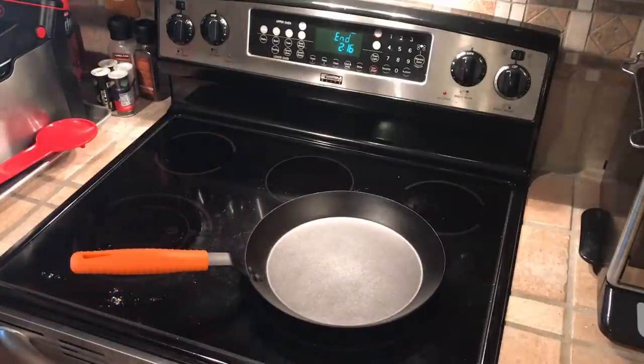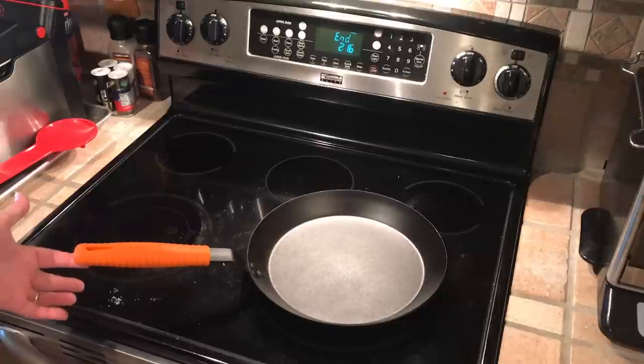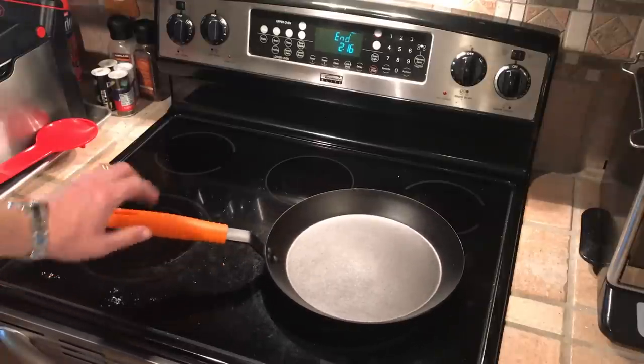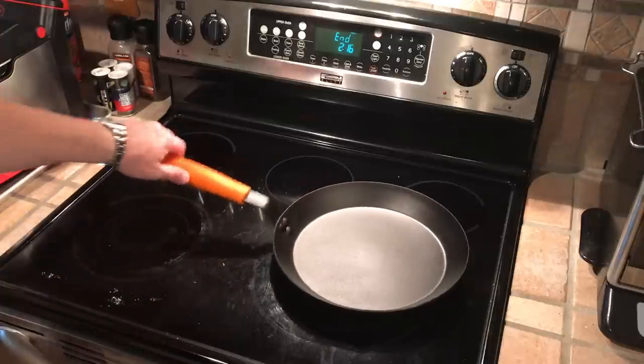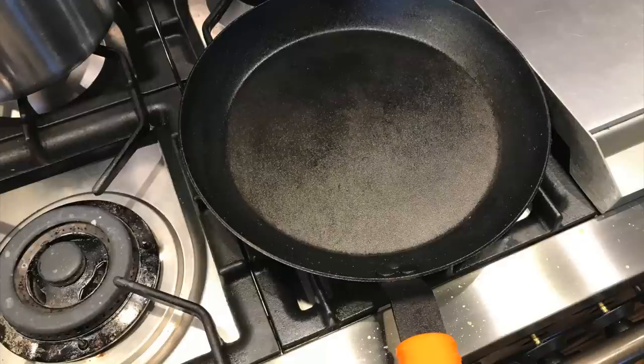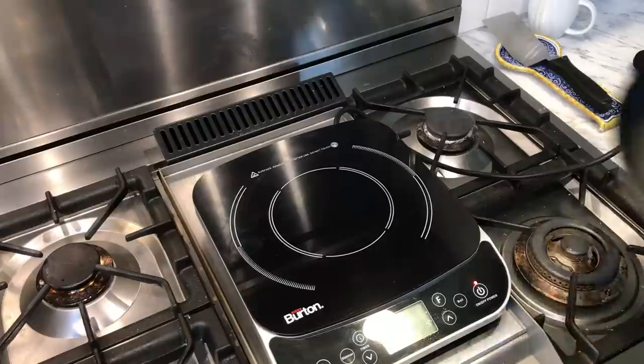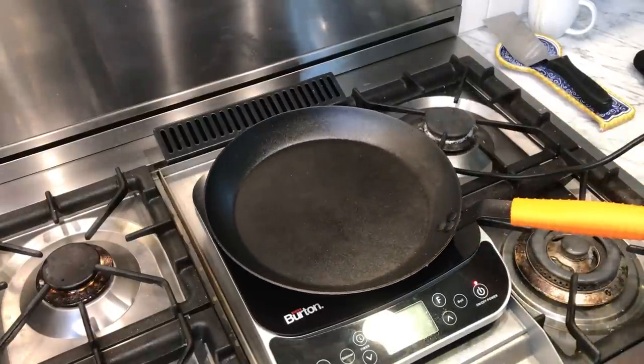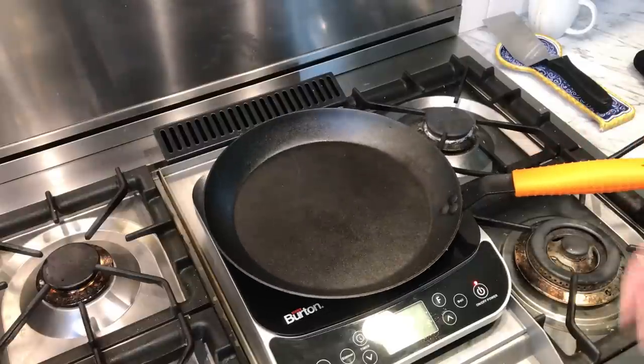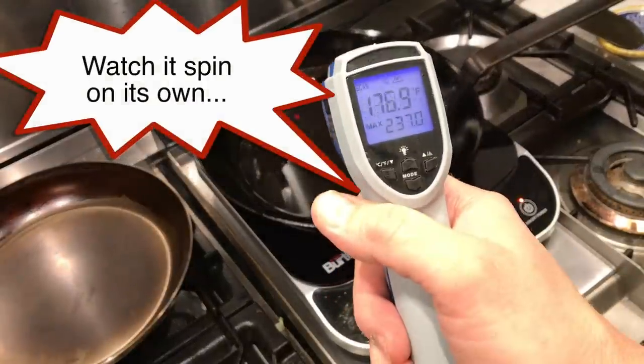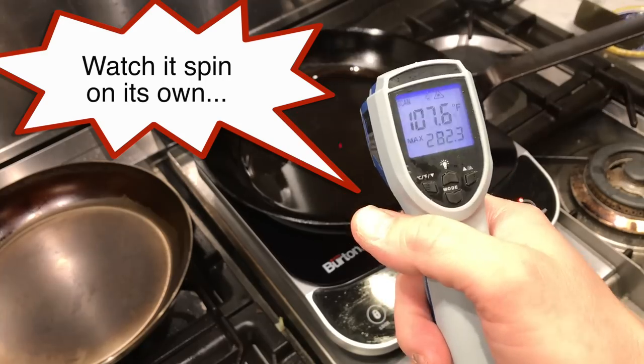Now I'd like to take just a moment to talk about bottoms. Due to warping issues, the bottoms of carbon steel pans are a source of headaches and frustration for many people, especially those with flat top electric and induction stovetops. Sometimes, as it heats, carbon steel will tend to warp, creating a high spot, causing a pan to either spin or not make good contact with the cooking surface. No big deal on a gas stove, but on a flat top, as the pan is heated by direct contact with the cooktop, this is a significant issue. In fact, in another video, I showed this warping happening in real time as my beloved Matfer pan warped on an induction burner. So this is a valid complaint.